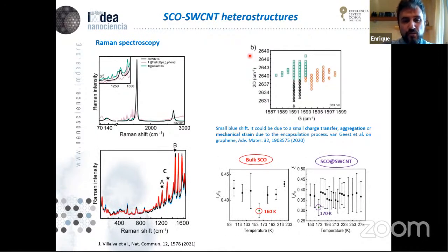We have as well tried to see if we could track the spin crossover in the Raman, but it was not so easy. But still, we focused on some of the peaks of the molecule, using this peak as a reference. Measuring the height, so the intensity, as a function of temperature, what we could see is that some of the peaks decrease their intensity at precisely the temperature of the spin crossover, this one around 160 to 175. It's interesting to see that in the bulk, so in crystals of the molecules, this happens at slightly lower temperatures than what we see in the molecules encapsulated in the carbon nanotubes. Okay.